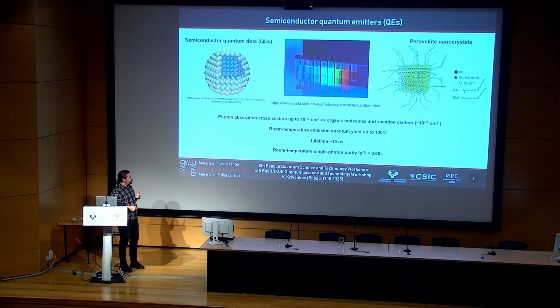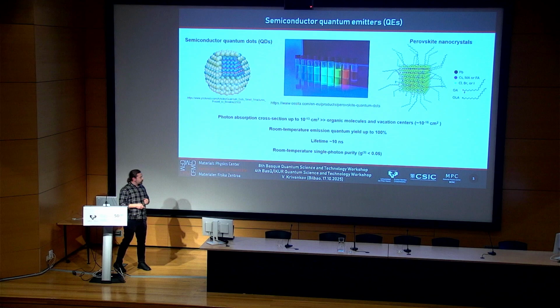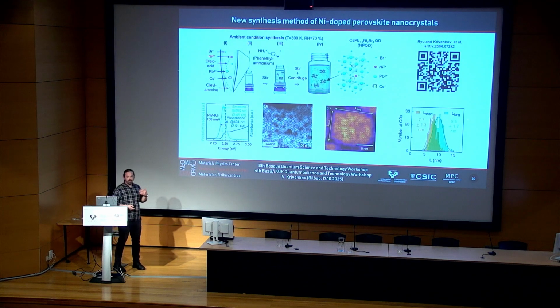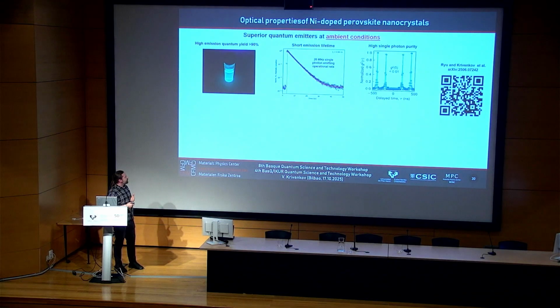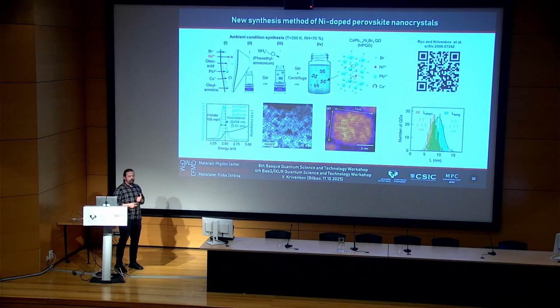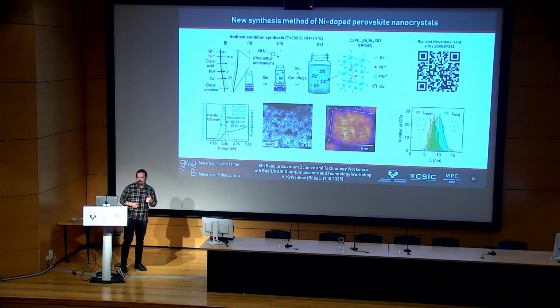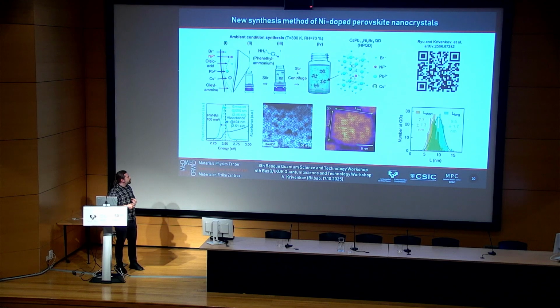Also, they have a short emission lifetime compared to many other quantum emitters, and they have very high single photon purity at room temperature, even below 5%. Recently, our research group has mainly focused on perovskite quantum dots, perovskite quantum emitters, and we developed a synthesis protocol which allowed us to easily synthesize very high quality perovskite nanocrystals with an almost cubic shape and very high uniformity. We can perform this synthesis at ambient conditions, at room temperature, so many research groups can reproduce it for their experiments.